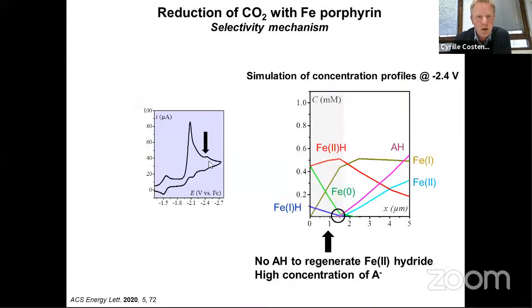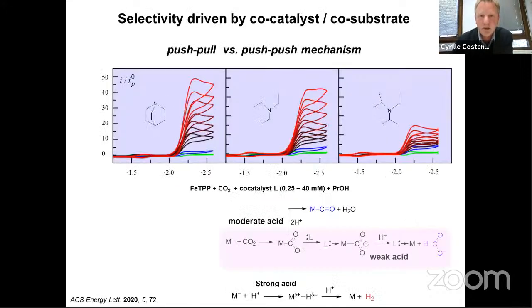Because if I go back to here, if you have consumed the acid, you have in the diffusion reaction layer a high concentration of the conjugate base of the acid, which here is triethylamine, because the acid was the protonated triethylamine. So now if you put the amine in the solution, you can see that actually you can boost the reduction of CO2, which means that this base, this triethylamine or other tertiary amine, can have a role in making the CO2 reduction more efficient.